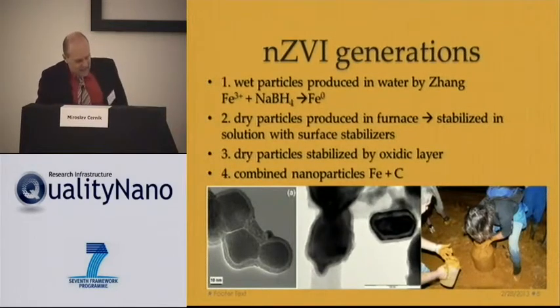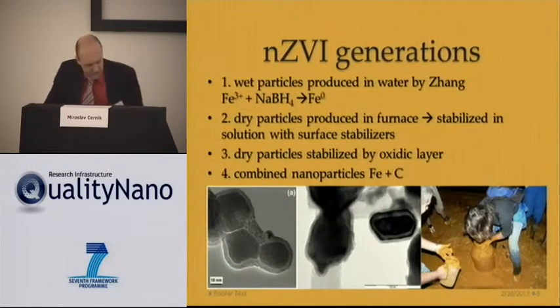Now we can say that there are already 4 generations of the zero-valent iron nanoparticles. The first generation was prepared in the laboratory by wet chemical reaction with borohydride. This is according to Professor Zhang of Lehigh University, USA. Then the second generation was particles produced in a furnace by reduction with hydrogen, and then stabilized with the surface stabilizers I showed before. Then my colleagues from Palacký University came with the idea to protect the surface of the particles by a very thin oxidic layer of the iron and stabilize them later before the application. And nowadays we work on combined particles which combine the effect of iron reduction and carbon sorption, so that there are particles which are combined.